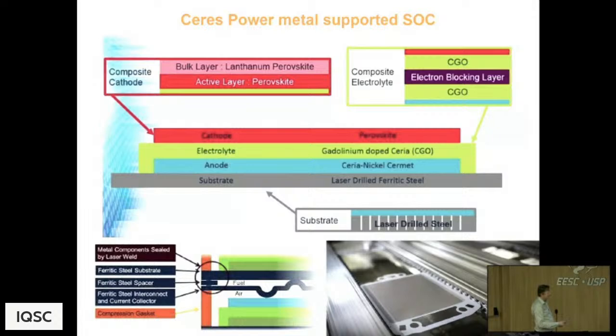The key advantage of all of this is that you can have a welded seal and a gasket seal. So almost the entire motivation for all of this effort is you can have a high integrity seal. You don't have to have a glass ceramic seal, and all of the other devices have glass ceramic seals, and they're a complete nightmare to engineer a robust and reliable device with. So you can have all the best chemistry in here, but if the seals don't work, the stack breaks. And what you find with most technology is you thermally cycle it up and down in temperature, the seal fails. The big advantage that Ceres have is that the seal doesn't fail. And that's one of its principal characteristics. Of course, you've got to get all of this right as well.